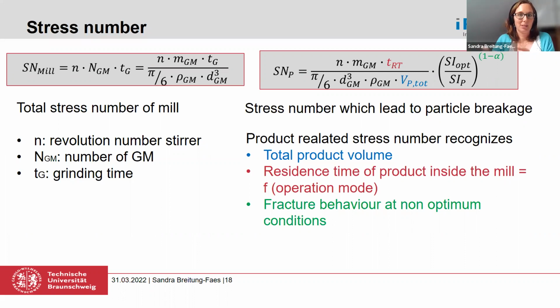As you know, the same solids mass, weighted by mass, might be different for different products as the density might change. And then I had this value where I compared the distance between the optimum stress intensity and the stress intensity which I adopted at my mill, because maybe it's not possible to use the optimum one, or not desired at least. And here this alpha value is also something like a material parameter which is reflecting the fracture behavior at non-optimum conditions.